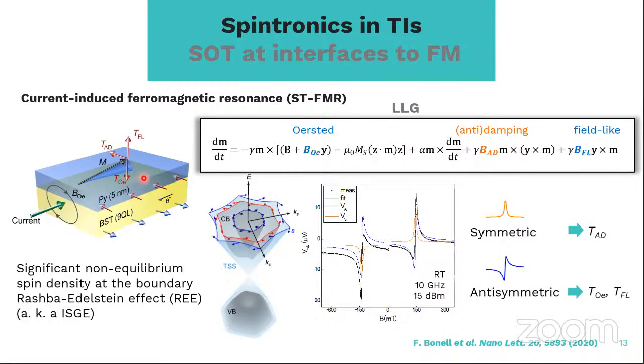Since you have to make this coplanar setup to measure the FMR, do you use any capping layer for the top? A capping layer, yes. We use aluminum, and then it oxidizes. So it's what we call aluminum oxide, but we don't evaporate aluminum oxide. We evaporate aluminum and then allow it to oxidize. I know that introducing those capping layers also shifts the resonance field somehow. I don't know if you tested this before. How do you differentiate both effects? That's not usually done.